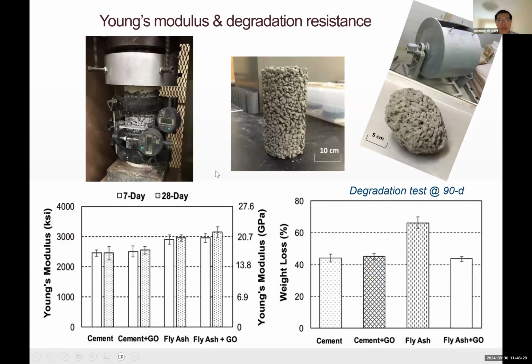So when you look at Young's modulus and so-called degradation resistance or abrasion resistance, again, the fly ash based pervious concrete actually has a somewhat higher Young's modulus, but when you look at the resistance to abrasion, they're pretty good, especially the one modified by graphene oxide. So these are very promising results.